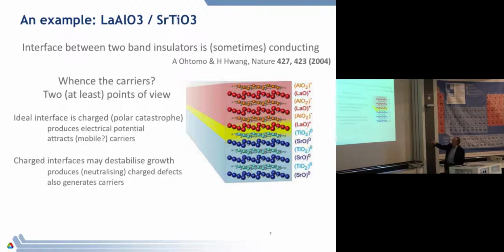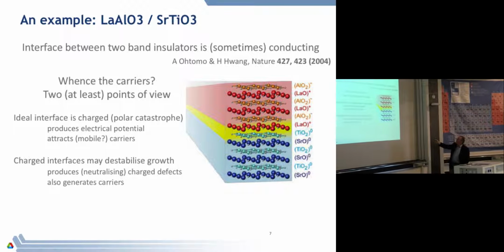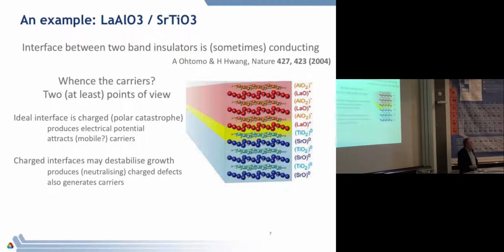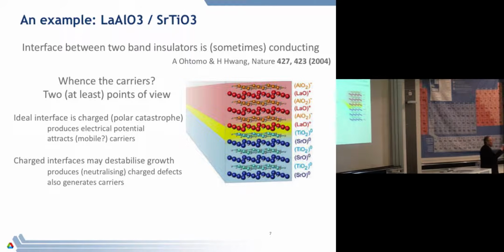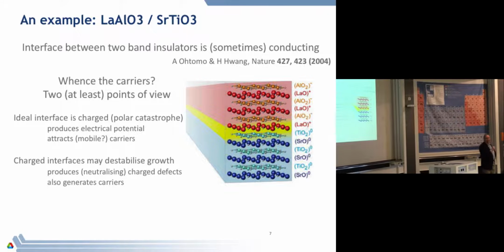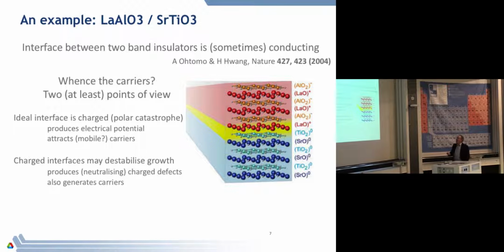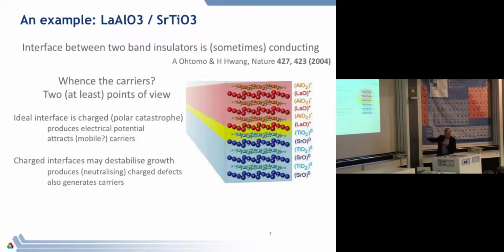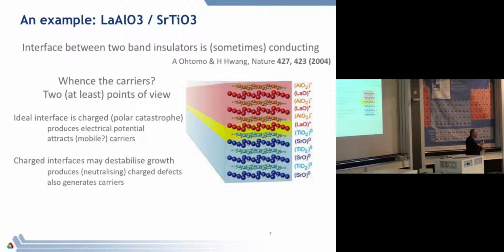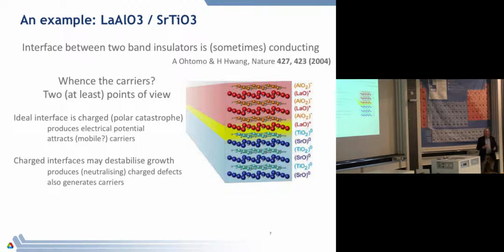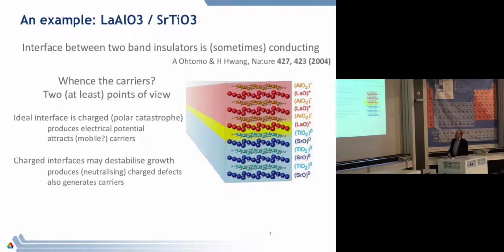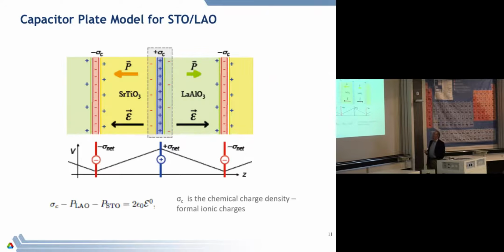So one way of thinking about this is that there's a natural dipole which ends on this surface. And you should all know that the divergence of a polarization is a charge density. And therefore that means that there is a formal charge which ends on this layer. It's a fixed charge. But because that charge is there, if I now sprinkle in carriers, the carriers will then run to this interface. And that's the idea. And with a number of complexities associated with it, that's basically correct. Okay.